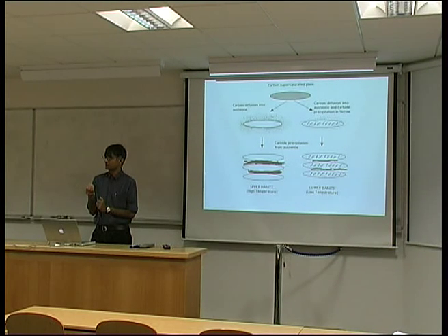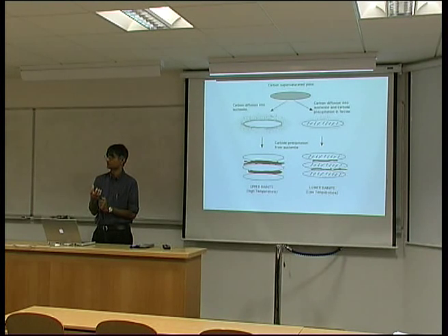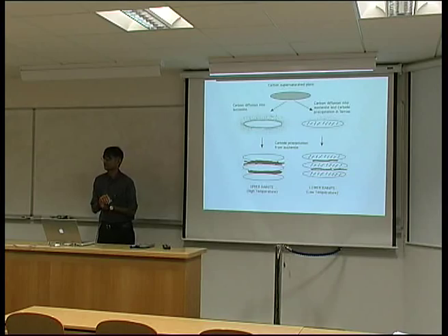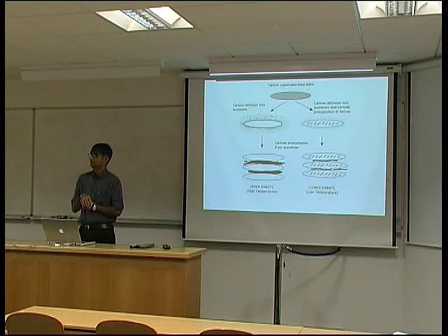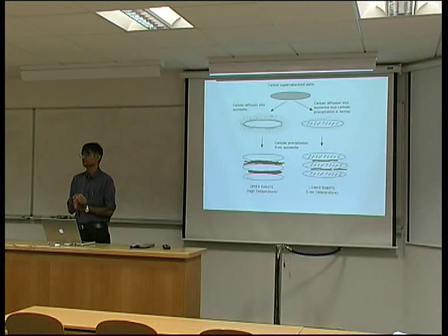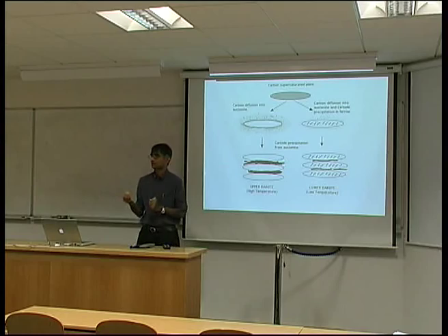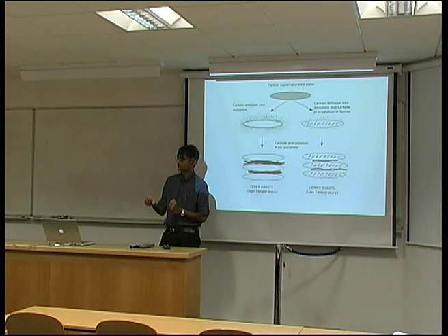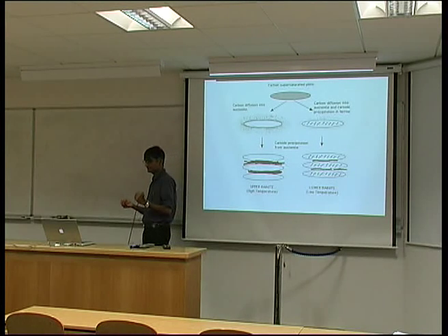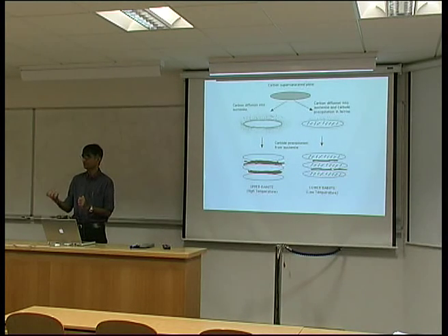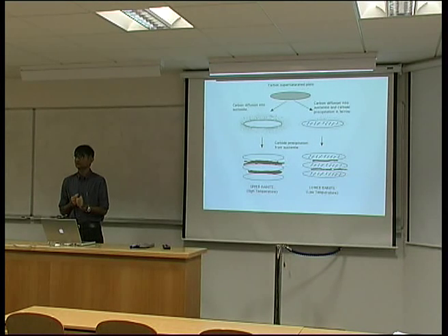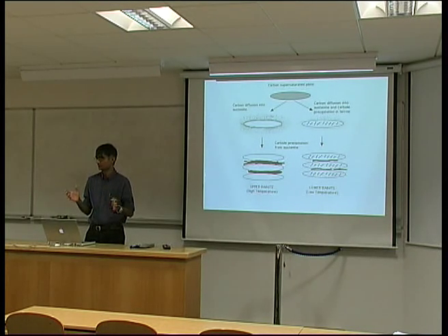In the context of cast irons — how you change a white cast iron to a grey cast iron — a white cast iron has most of the carbon tied up as cementite, whereas in grey cast iron you've got graphite. The key compositional feature is silicon. You add sufficient silicon and you suppress the precipitation of cementite, because silicon doesn't dissolve in the cementite lattice. With sufficient silicon you end up with grey cast iron with flakes of graphite, whereas with a low concentration of silicon, you end up with very hard white cast iron.